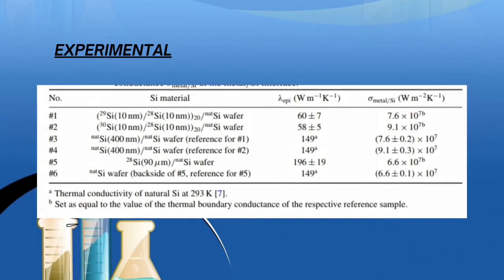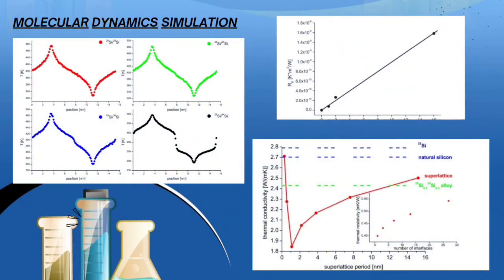Next, the graph on the left is about the simulation result for the thermal conductivity of the pure 28 silicon system. Lambda 28 equal to 2.79 W/mK is far below the experimental value for bulk silicon. The reason is that the boundary conditions imply that we simulate a nanowire, not a bulk lattice. Here, a reduction of thermal conductivity due to size confinement is indeed expected.